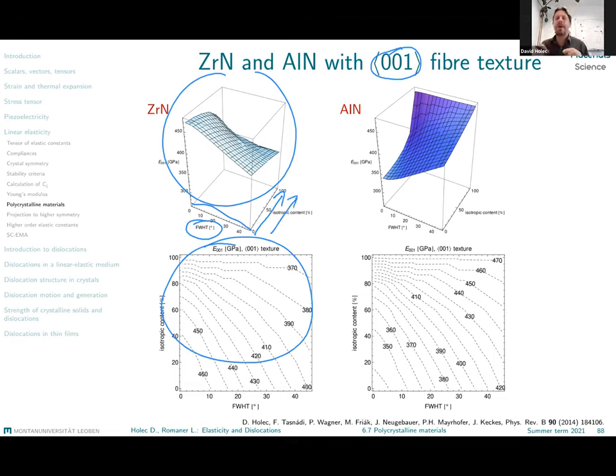If, on the other hand, I come to a perfectly single crystalline material, so I have no grains, no grain boundaries, and essentially all the grains have exactly the same orientation, so the full width at half maximum is zero. All my grains have the same orientation. The distribution is just a single delta function peaked at one orientation. I come to this corner and here I would have now the Young's modulus E100 in the 100 direction because this is the orientation of my grains. On the other hand, this point here would correspond to a perfectly isotropic material, material which is represented by the Hill average of our polycrystalline aggregates.